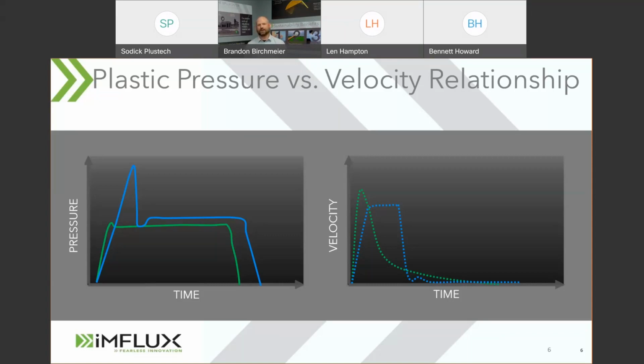The parabolic slowdown you're seeing in that velocity is allowing us to pack that part out while we fill it. It's during that controlled slowing, and as you can see, we always get this parabolic relationship, especially in a constant nominal wall thickness. As that velocity slows down, we are able to pack that part out, which doesn't require us to have to transfer over into a pack and hold phase. That parabolic slowing down is actually packing that part out while we fill it out. You get a lot of advantages, which I'm going to cover.